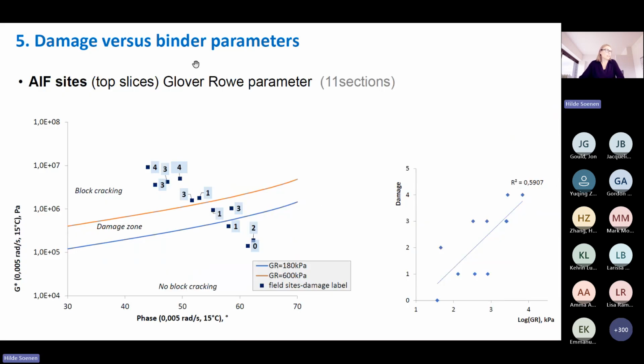So in this slide, I now look at the AIF sites we investigated, only the data from the top slices, and we look at the Glover-Rowe parameter. So in total, we have 11 sections, and they are plotted in a black diagram. In our study, we used the Glover-Rowe determined at 15 degrees and at the very low frequency level. And you can see the 0 is the lowest and the 2 with a number 4. So these numbers are damage levels. The 2 with a number 4 are on the high side. You could argue that this 3 could be an exception and this 1 could be an exception, and also the 2.